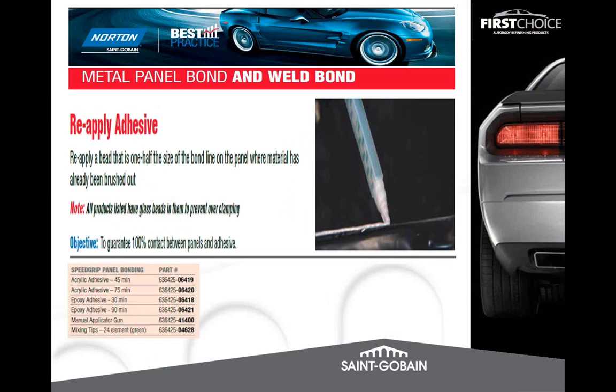So we want some ooze out knowing that the glass beads are in there, and it'll stop you from over clamping, so it's physically impossible to push out all the glue. But ooze out is a good thing to know that we have full contact with the new panel and the substrate or the area that we want it attached to the vehicle. So we reapply a bead of glue, as it says here, about half the size of the bond line, and you'll see that very well in the video. Where the glue has already been brushed out. The reason for that is it allows the glass beads to do what it needs to do, but it also guarantees 100% contact between the two panels.